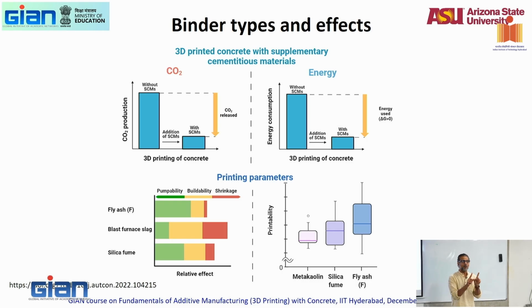Water to cement ratio, but we have to look at water to cement ratio slightly differently here. Don't say I will reduce the water cement ratio. You can say that I will increase the particle density, because particle density, your yield stress, is what you want to maintain to make it extrudable and buildable. What you want are particle contacts. I want now to play around with the different sizes of particles, and that's where limestone powder is suddenly a wonderful additive for 3D printed concrete.